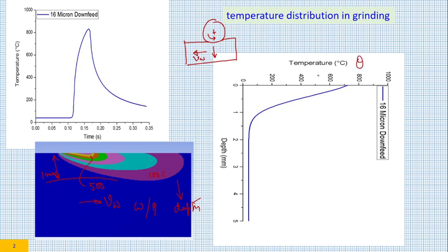So this axis is temperature axis, and this axis is depth axis. In this, the measured temperature is around 700 plus degrees centigrade. That is the rise in temperature, and it becomes almost ambient temperature at a distance of around 1.4 millimeter. So within 1.4 millimeter, there is no signature of grinding. Grinding temperature is very high. Not only that, the space gradient of temperature is also very, very high.